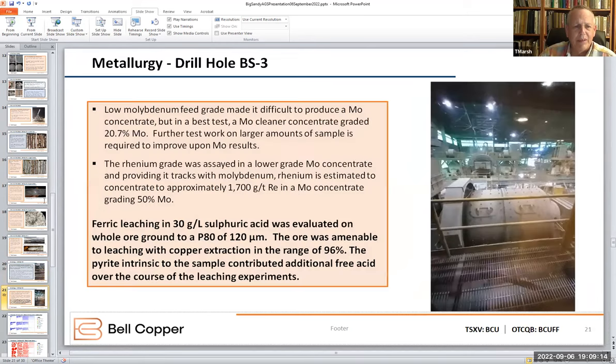We ran ferric leaching, 30 gram per liter sulfuric acid on ground ore. So this isn't really representative of an in situ process, but we found we could get plus 96% of the copper out by leaching it with sulfuric acid. We also found that the sample itself generated free acid during the leaching process. So we don't have an acid consuming environment. We've got an acid generating environment, which would make it a little more amenable to an in situ idea